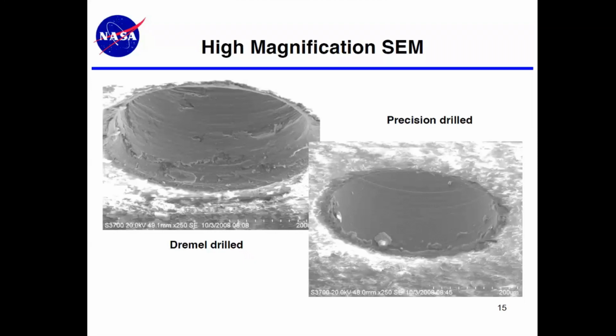So with these materials, again, we did most of our work just trying to capture the patterns. We weren't able to do full characterization, but we did learn that as long as the holes were spaced fairly far apart, more than 4 or 5 diameters from each other, and if the holes were high quality and didn't have a lot of texture or roughness around the edges, then the fatigue properties weren't as bad as one would expect. So next chart, please.